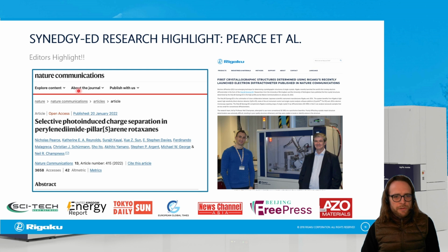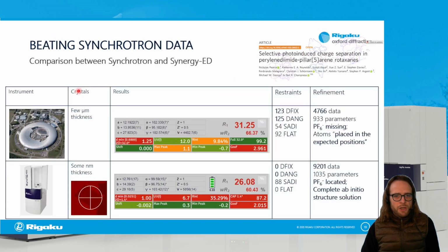Just to highlight one of them, we did this one collaboration with the group of Neil Champness, which actually pushed this publication into Nature Communications, really into a high-impact journal, because of this additional data we could provide from a Synergy-ED, which turned out to be much stronger than the data that could be acquired for the same crystals on a synchrotron, on Diamond. So here, the Synergy-ED totally outperformed even a synchrotron.